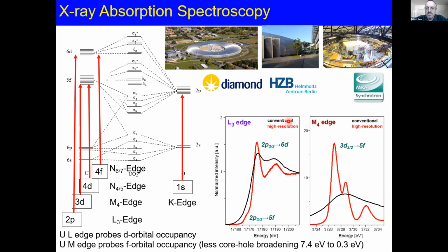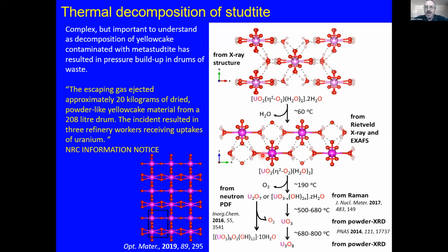And using some high resolution XAS, we can now start to resolve features in particularly the M-edge that you can't really see using conventional spectroscopy. This is important because you get less core hole broadening in the M-edge compared to the L-edge. So we'll start off by looking at studtite. This was this unusual mineral.